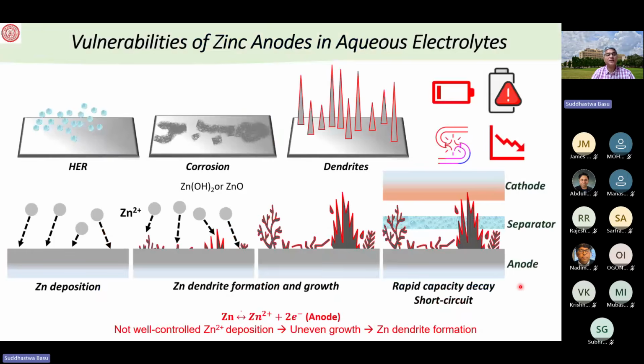Okay, so the next topic that I want to talk about is the zinc aqueous battery, and we have developed a MOF structure which is like an SEI for the anode electrode, or the negative electrode, and which protects from the growth of dendrite. We all know that in the zinc battery, we use zinc as the anode electrode, and zinc hydroxide or zinc oxide formation is there because zinc sulfate is used as the electrolyte and zinc as the anode material.